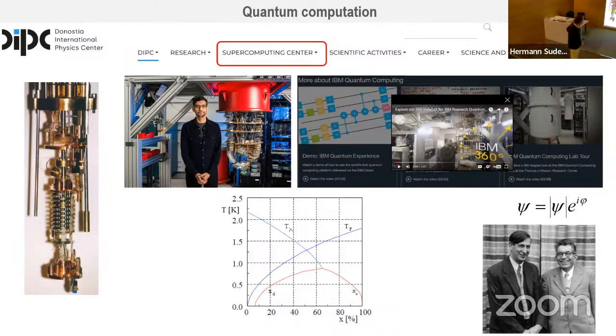But maybe it's good to remember that the reason why it works is because of these two persons, particularly Heinz and Fritz London. Fritz London, you know, from the London equations for superconductivity. Heinz London is not so well known, but he discovered actually this phase diagram, which is actually beautiful. So in the same way that you have f electrons, when the f electrons are localized, actually you have a Fermi temperature which is high. When you start delocalizing the f electrons, you actually start populating with heavy electrons the rest of the path in some sense, so you decrease the Fermi temperature. And therefore you get high effective masses. And the same happens here.